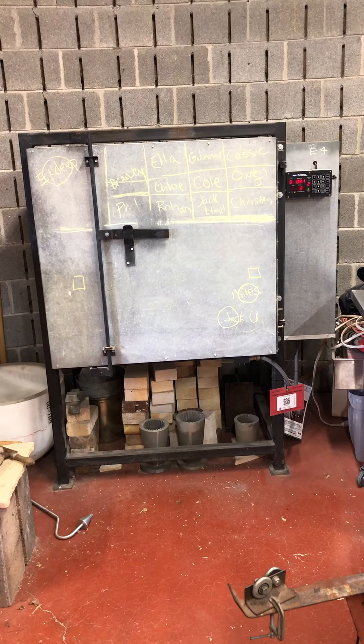The finished fossil needs to be put in the annealer. This annealer is already at 950 degrees. All the pieces made in the glass studio during the week are loaded into this kiln called the annealer. At the end of the week it is programmed to cycle down very slowly from 950 degrees to room temperature — it takes about 12 hours to cool down. That slow process of cooling down the glass, which is called annealing, allows the glass to release stress and prevent cracking. And those are the steps to make a glass fossil.